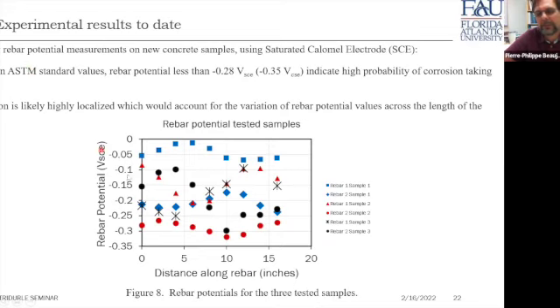And what I want to focus on very quickly in this measurement is this plot right here, which actually shows the rebar potential, which is called vs SCE, as a function of the distance along the rebar, which in this diagram is shown in inches, for the different samples, sample 1, 2, and 3, and for the different rebars. Now you remember sample 1 shows very little corrosion, sample 2 is actually subject to some cracking, and sample 3 is really badly cracked. So you actually can see in black and red that really a lot of corrosion is actually taking place in both samples.